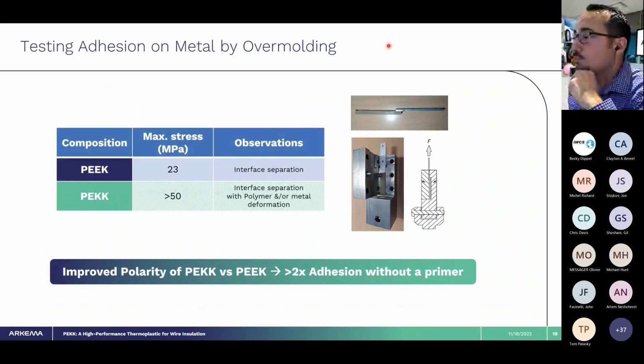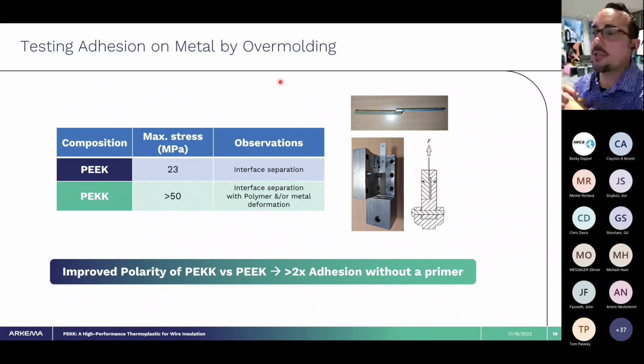Briefly, I mentioned we have this additional benefit of having a higher polarity, being a PEKK, additional ketone. What we're showing here is a rough test we did, over-molding PEEK versus PEKK onto a bare metal substrate. So no primer here to ensure good adhesion, just the two materials themselves, on a clean, properly prepared metal surface. What you see is about a 2x increase in PEKK over PEEK in the adhesion test.